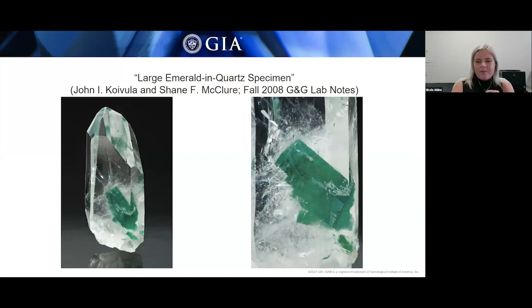It is presumed that the emeralds did form first, and you can see that evident by how the emeralds are there at the surface of that quartz that you can see in that photomicrograph on your right. So again, they're presumed to be grown first, and the quartz itself measured about 74 millimeters long, and the largest emerald in there measured about 23.5 millimeters long. So they're actually quite large inclusions that we're seeing in the quartz.